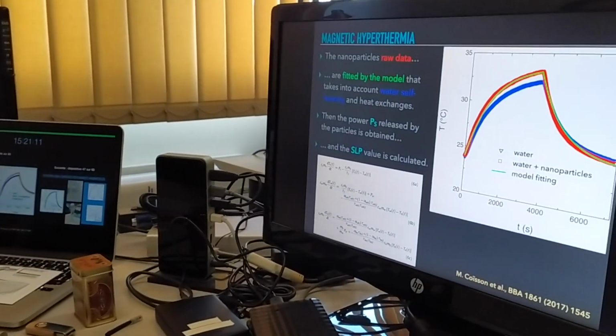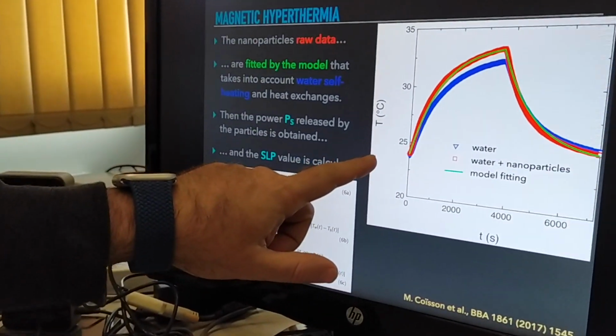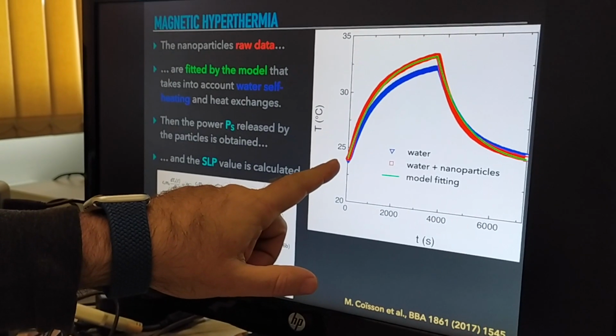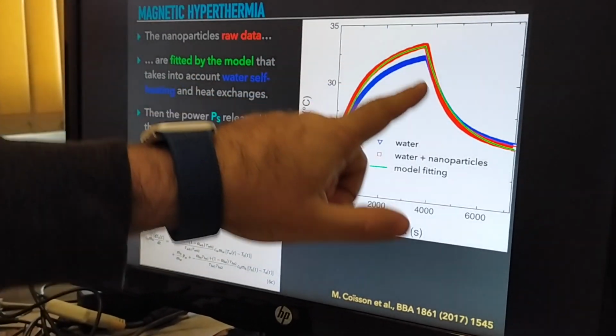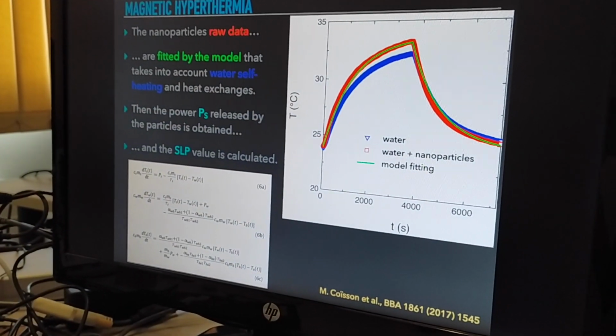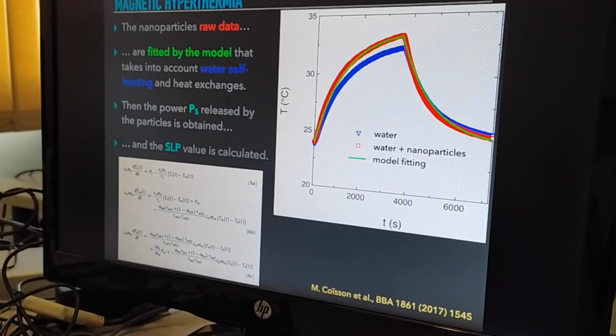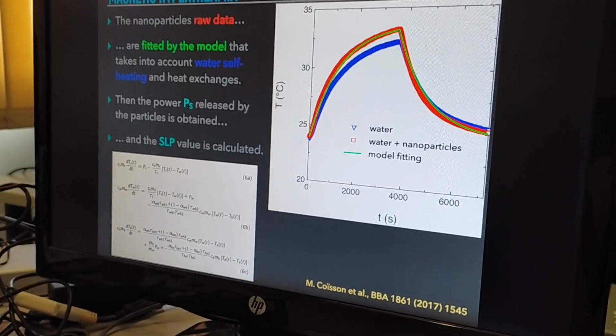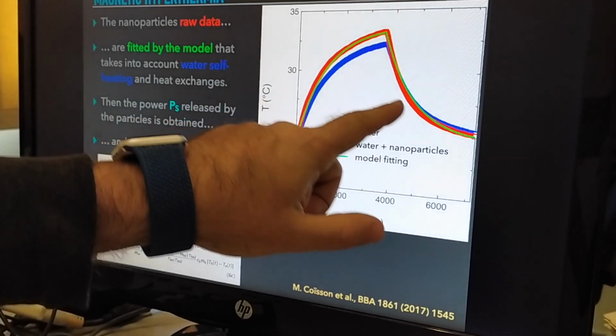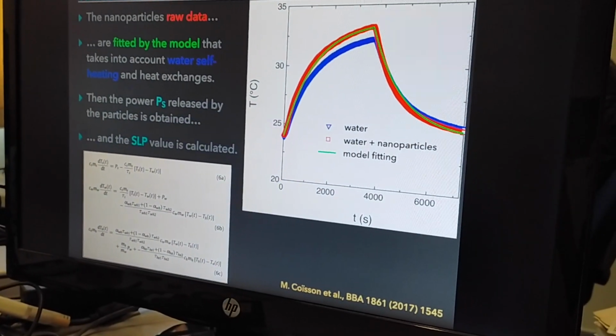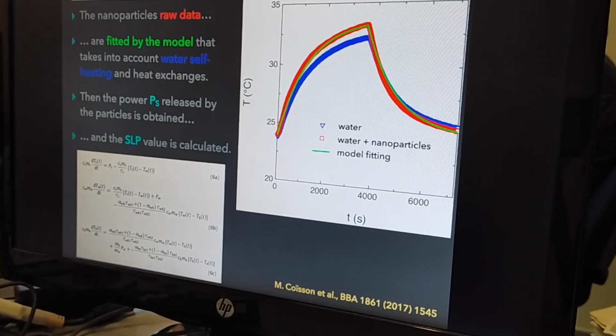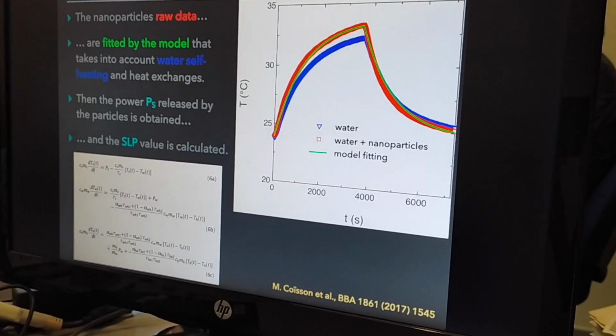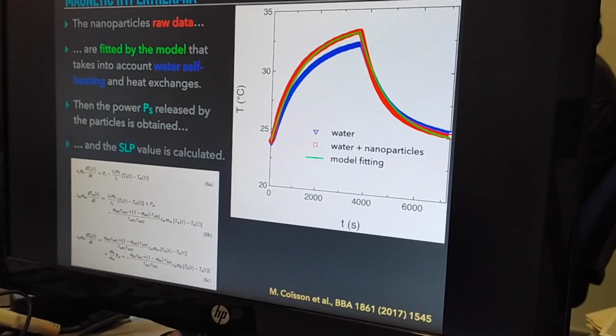A typical magnetic hyperthermia experiment consists of 2 measurements. One is the measurement that we discussed in the previous minutes, the red curve of the magnetic nanoparticles dispersed in water. But a second measurement must be done with just the water without the magnetic nanoparticles, the blue curve, because as you can see, there is a spontaneous heating also of the water without the nanoparticles.